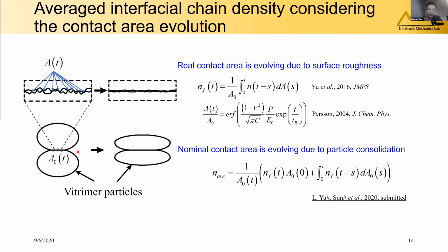So to consider this effect, we use the Persson's model to describe the area evolution and obtain this integral form for the average chain density. Here dA is the increased interface area during the time ds, and this incremental area experienced the healing from time s to time t. So this formula has summed up the chain densities contributed from all the different incremental areas in the time history.